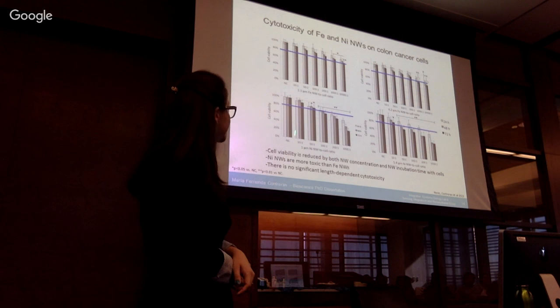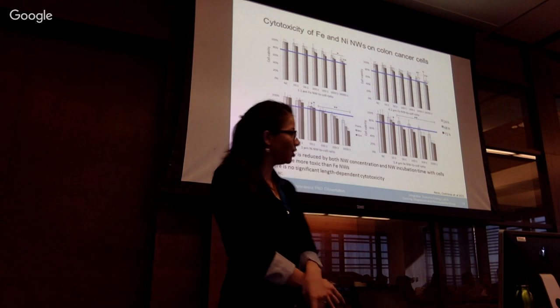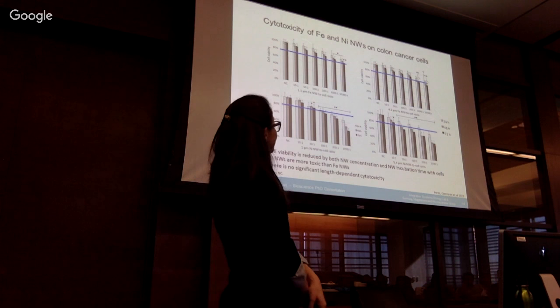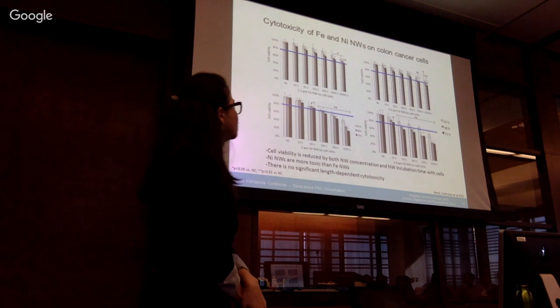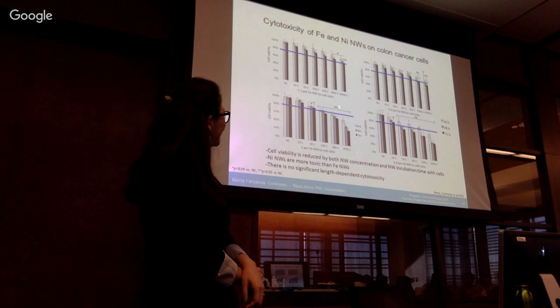viability reduction correlates with both the nanowire concentration and the incubation time for the two materials and the two lengths observed. Secondly, that nickel nanowires are more toxic than iron nanowires. Iron nanowires are tolerated for higher concentration and longer incubation times. And that there is no significant length-dependent toxicity.